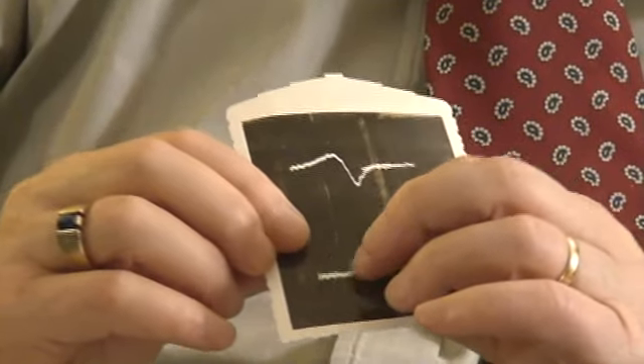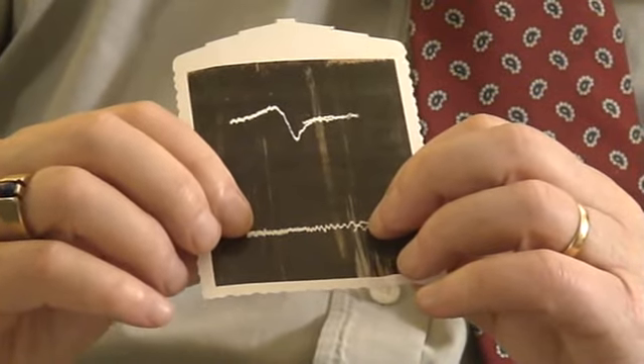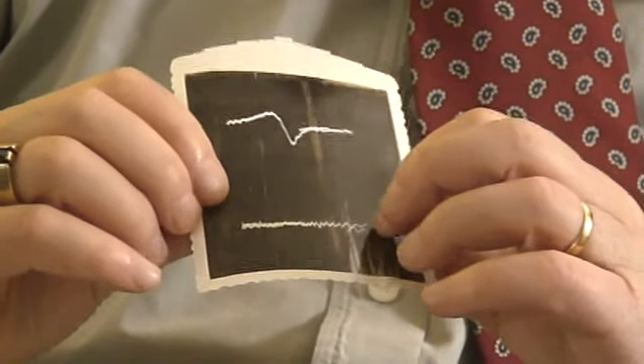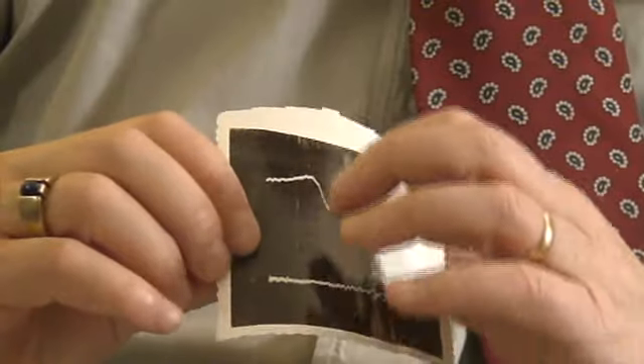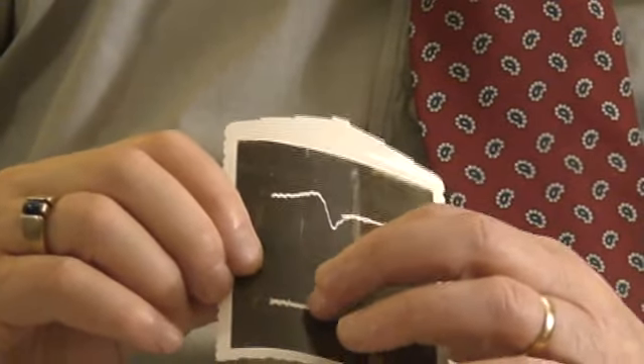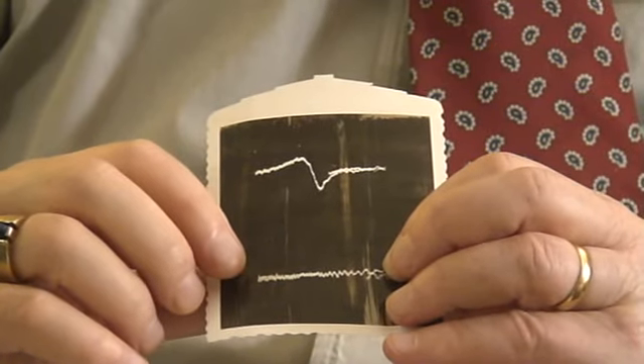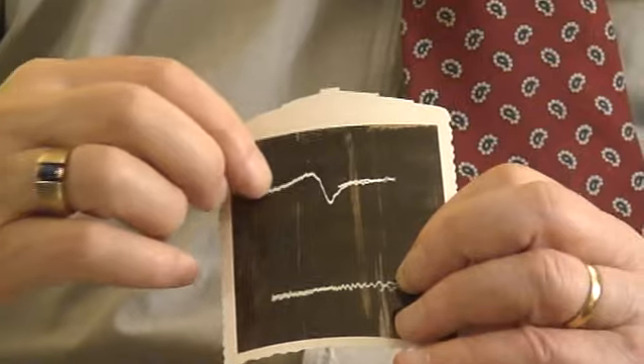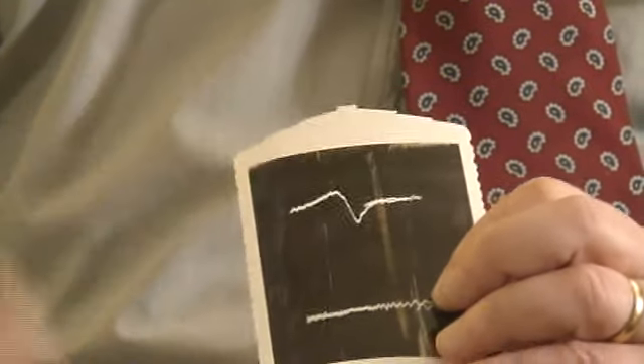You want to describe what these are? Well, this is a letter from Charlie Slichter that came after the telegram, giving me more details of the experiment that they did. And this is a Polaroid picture. Here is the nuclear resonance of lithium metal without the microwaves turned on, which would hit the electron spin resonance. There's nothing there. There's presumably a tiny resonance signal here, but it's too small to be seen. And then when you turn on the microwaves to hit the electron spin resonance, you suddenly get a very nice nuclear spin resonance as shown here.